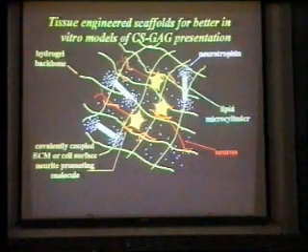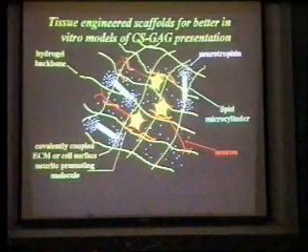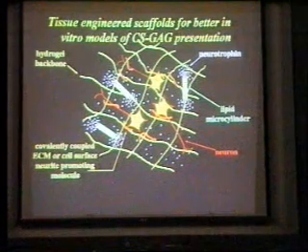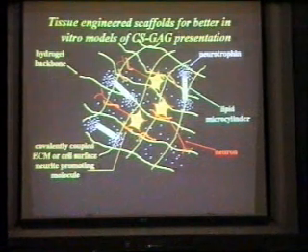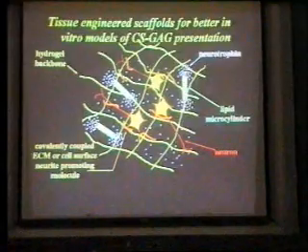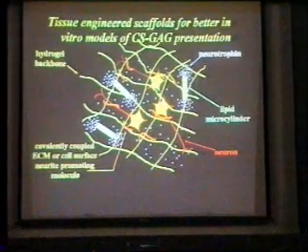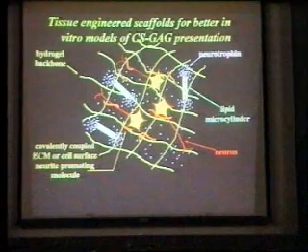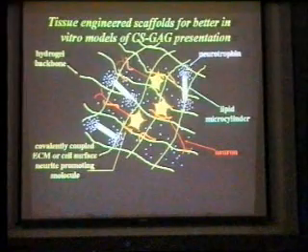And the reason we had to do this in gels and not in 2D is because if you take these sugars and immobilize them on a surface or absorb them on a surface, they're very, very hydrophilic. If you just absorb them, they lift off and go into the solution. If you immobilize them, because they're so hydrophilic, cells don't attach to them. So if you don't have a neuron attaching, you can never really ask the question, is it inhibitory to growth, because it never grows, because it never attaches, right? So we used this 3-dimensional system that we had developed for the peripheral nervous system, and we coupled GAGs to the backbone of these gels.